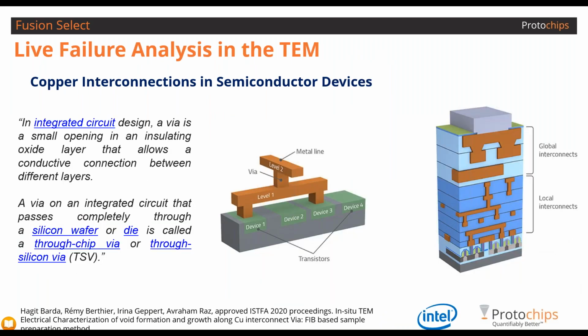And this method was used recently during a very successful collaboration between Intel in Israel and Protochips. They contacted us because they wanted to observe a very specific via in a very complex stacking. A via is this metal connection that links different layers, different levels of a very large stacking, a very complex device. As a matter of fact, sometimes those vias fail, and they wanted to observe how such a structure fails and disconnects when you apply a very high current through it.